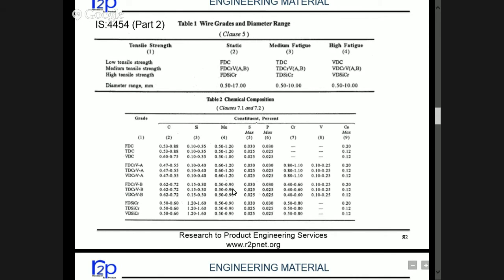The table below gives the chemical composition. Typically in this VD silicon chromium, the carbon is 0.5 to 0.6, silicon 1. So it's a silicon steel, you can see. Silicon is deliberately added. Normally you have seen the percentage of silicon is restricted below 0.2, 0.3, even in fractions. But in the case of spring steel, silicon is deliberately added, right? And then manganese, sulfur, phosphorus are in restricted quantity, and chromium is there, right? So selection can be done from this table depending upon the fatigue, the number of cycles that the spring is to encounter.